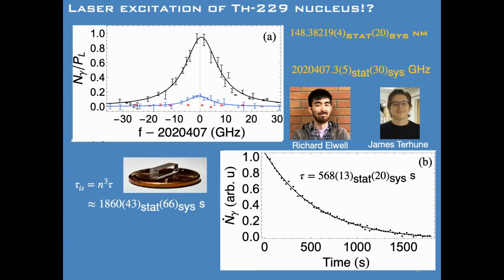I've been saying that the lifetime is thousands of seconds, but that's in vacuum. In the crystal, there's an index of refraction, so the photon density of states is n cubed higher. It's a magnetic dipole transition. The magnetic dipole isn't screened, so it just goes as n cubed. So if you see 600 seconds here, that means in vacuum it's about 2,000 seconds, which is what we had expected in our work.